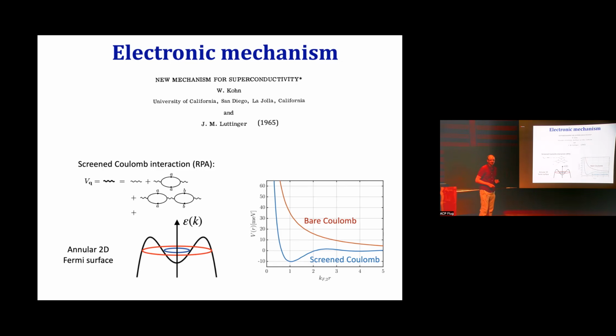This is zero frequency. This is the effective attraction at zero frequency. Yet this is a very rare mechanism of superconductivity. You have to have just the right conditions to have this. Let me also mention in this context that for this calculation that I'm doing, the fact that I have this particular shape of Fermi surface actually is crucial. If I did the same thing just with a single Fermi surface, it just won't work. You would get some superconductivity, but it would be too weak.